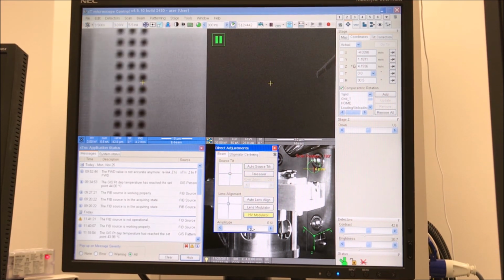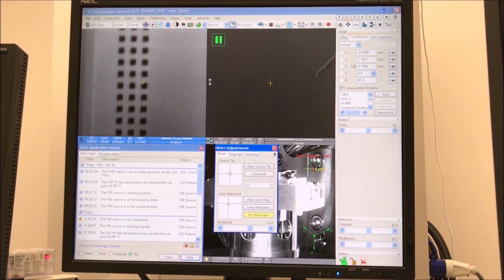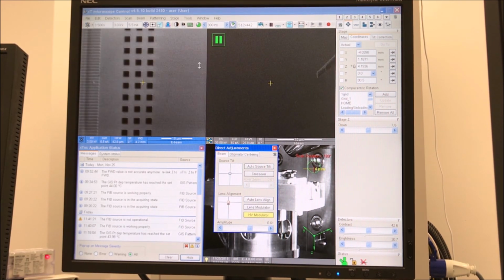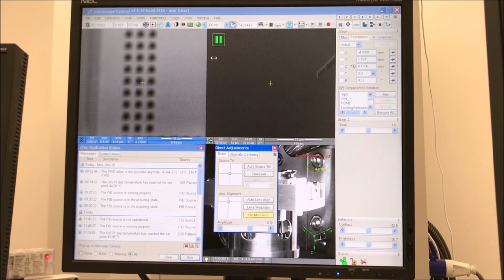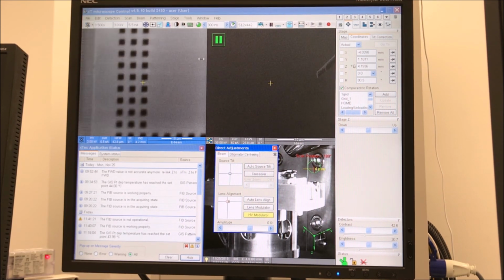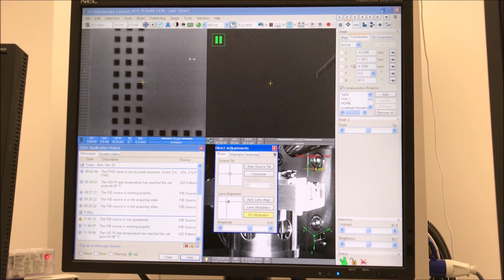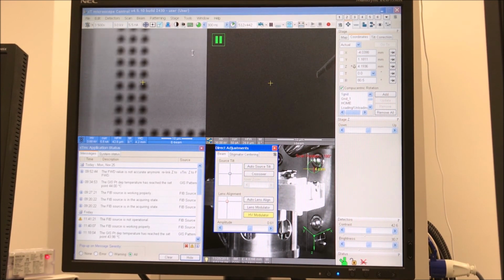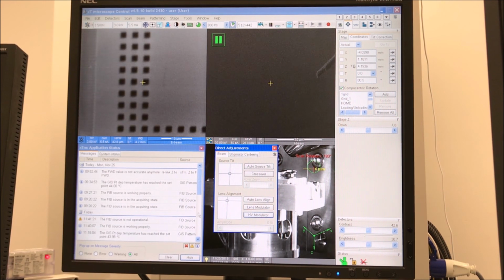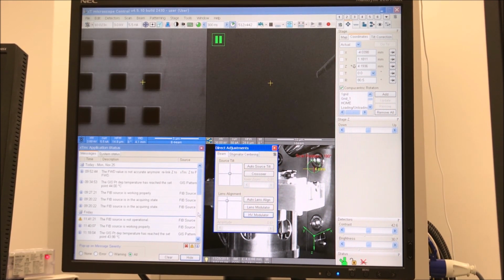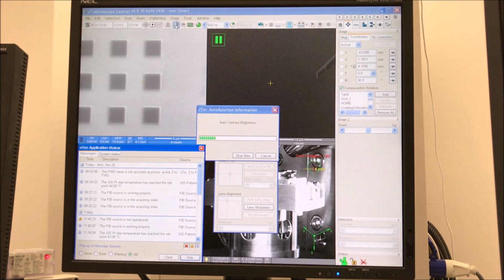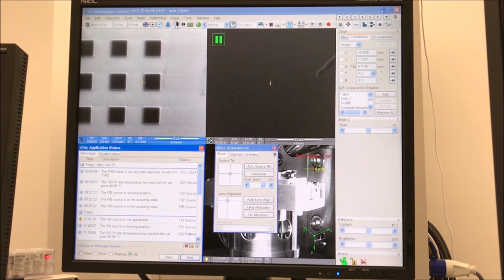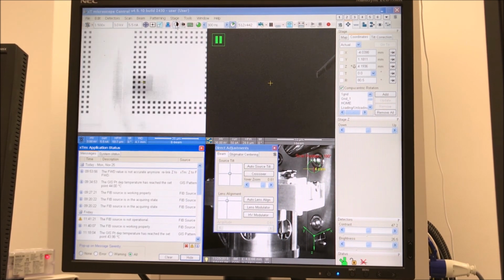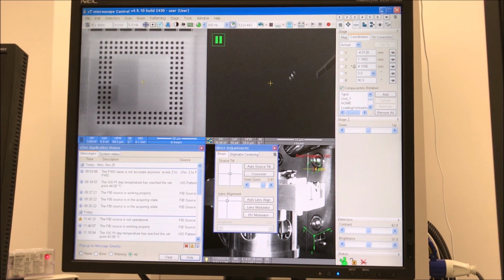So I'm doing the gun alignment, and now I'm doing the lens alignment, adjusting those crosshairs until the image shifting is minimized. Again, this is strongly dependent on your beam voltage and your beam current. And now I'm adjusting the stigmators to get the sharpest image possible. And so E-beam alignment is now done. Go ahead and get a good focus. And now I'm going to make the lamella right in the middle of that pad.